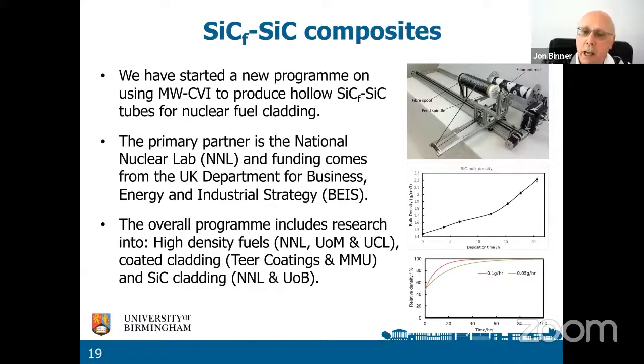up very nicely. And you can see there the estimated time to different densities, depending whether we're getting 0.1 grams per hour or 0.05 grams per hour. And it's suggesting, because we know we can get the 0.1, we're going to be 40 or 50 hours to make these samples. It's a long time, is 40 or 50 hours, but it's a lot better than 1,000 hours.